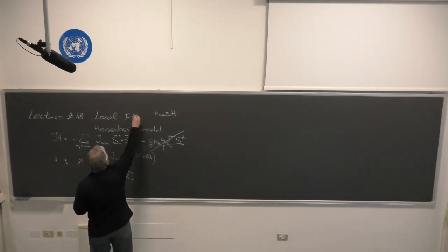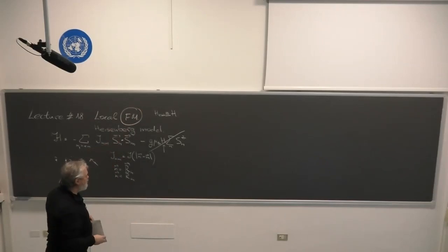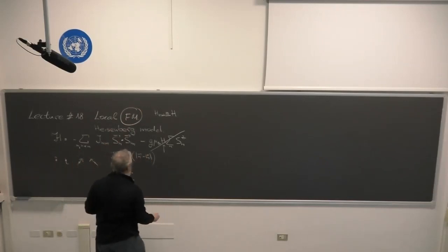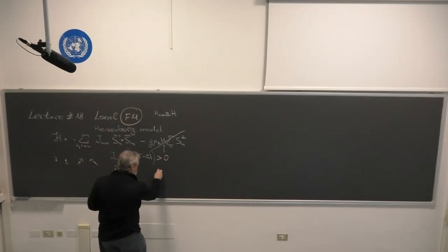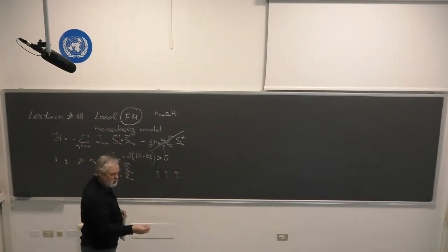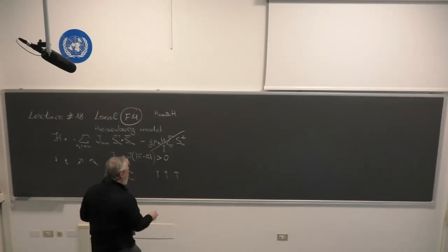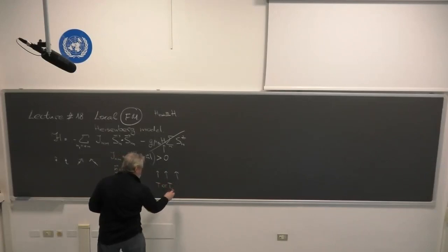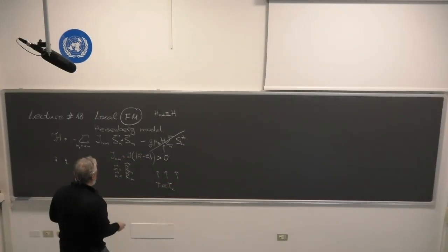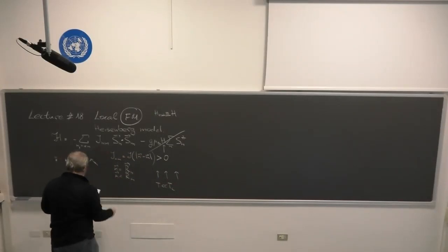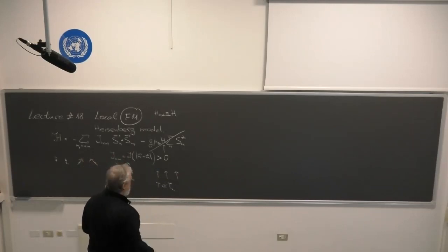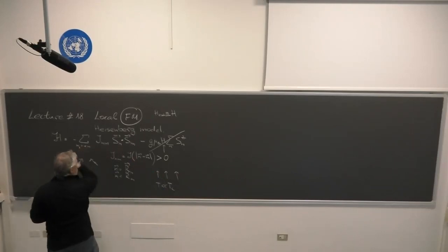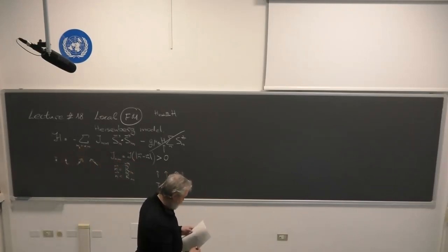Then, since I told you in the title of my lecture, it's a theory of local ferromagnetism, I will consider that all exchange integrals, J_nm, are positive, which means ordering spins parallel to each other, which happens, as we know, through the phenomenological models, at temperature much lower than Tc. We will see also what Tc is. Since all exchange integrals are positive, ordering spins parallel to each other will minimize the energy, because the scalar product is then 1, and you have minimal energy corresponding to this ordering.